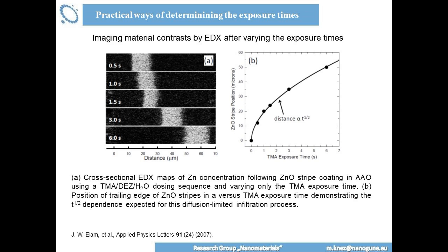Now, if you look into the stripe position then versus the exposure time of TMA, you have this kind of curve, and we will come to this curve just in a second again. It is important whether this curve is linear or not, because this defines whether the reaction is diffusion limited or whether it's chemistry or reaction limited.